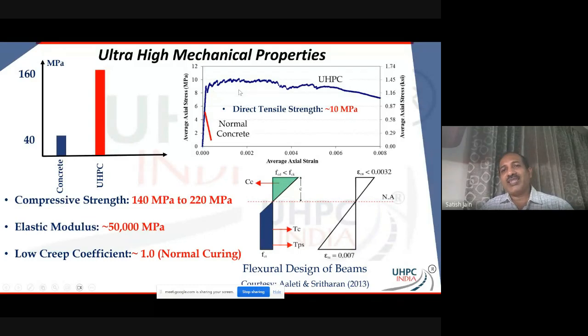That is what gives UHPC the energy dissipation characteristics, right? Which means that in this zone, when cracking happens, there is not just one crack or two cracks. There are multitudes of cracks that are going to happen, and those cracks are going to be extremely fine. So fine that you can call them impermeable cracks as well, because most of them are not visible to the naked eye in these early stages until that one crack gives way, and that crack starts opening in the strain softening area. But that's the beauty, the tensile toughness is huge. And this is what you can use in the design.